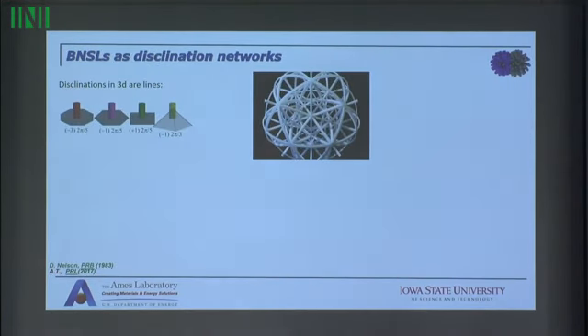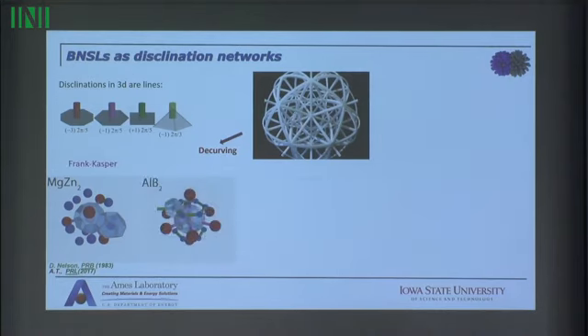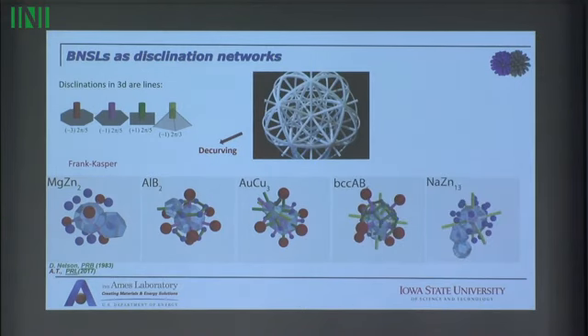Now, one thing that you can do is you can decurve by disclinations. And if you just use these type of disclinations, you get this particular structure with magnesium zinc 2, and for those familiar, that is a Frank-Kasper phase. What happens is that the 335 polytope has the ability to have other types of disclinations that are allowed by symmetry, and when you start decurving using those, you start getting all the superlattices that we have seen before.